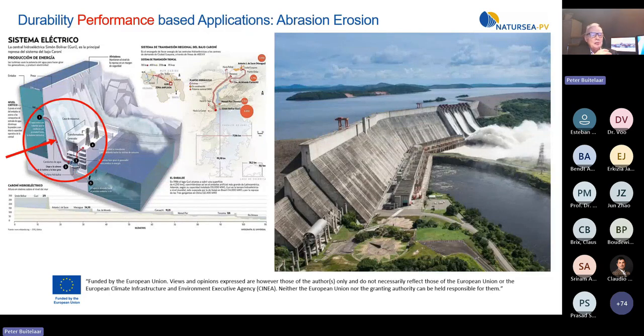The same ASTM test was done in the laboratory of Edelca in Guri, Venezuela, in the early 1990s, to investigate the suggested solution to protect the existing steel-lined inlet to the turbines with an abrasion-resistant UHPC concrete and avoid further damage to the turbines. The test resulted in previously unseen low figures. The problem was that the steel balls eroded when they touched the very hard calcined bauxite aggregates of the UHPC.